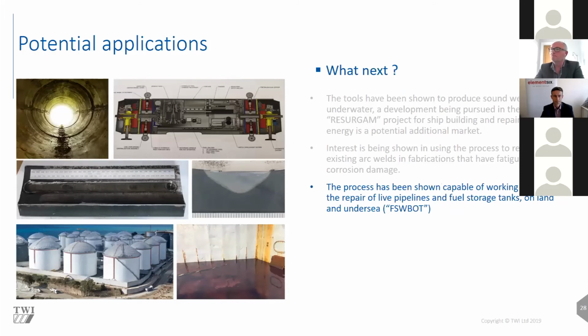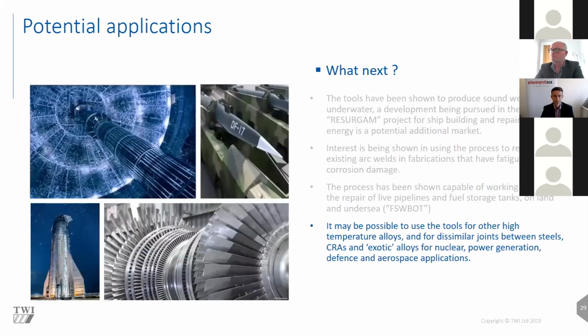As well as being able to weld underwater, we've actually shown that the process works under oil. And we've been working with one partner to develop a system which uses a pipeline inspection gauge, or PIG, which can travel down a live oil pipeline as the oil is flowing, detecting defects in the pipe and actually welding repair patches over those defects in the pipe. That's generated quite a bit more interest in the ability to weld things like fuel tanks without needing to drain and purge them. We've also been able to weld dissimilar materials, so welding things like steel to materials such as corrosion resistant alloys and some other exotic alloys used in the nuclear industries. And so again, that's creating a lot of interest in potential applications.